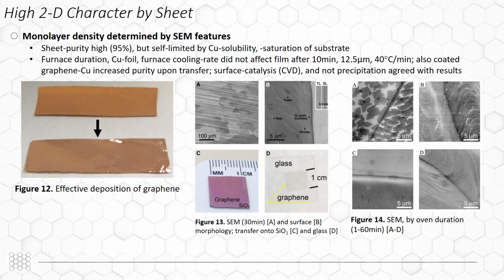Imaging analyses instead presented monolayer purity greater than 95%, and foil thickness independence of a surface catalyzed process through self-limiting copper substrate solubility and saturation.